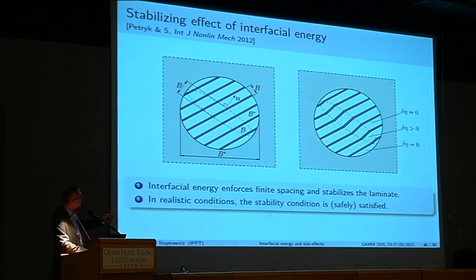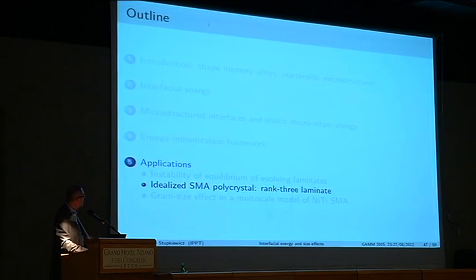Anyway, one can show that if the material wanted to localize in such a mode, there would be some small interfacial energy contributions of the kind of the elastic microstrain energy I was discussing before. And that energy stabilizes the laminate. So at the end, thanks to the interfacial energy, such an evolving laminate is stable. So it's good news for us. We can still stay in the world of evolving laminates, which we like. And this condition is safely fulfilled for most of the practical situations. Okay, so if we can do laminates, let's do laminates.